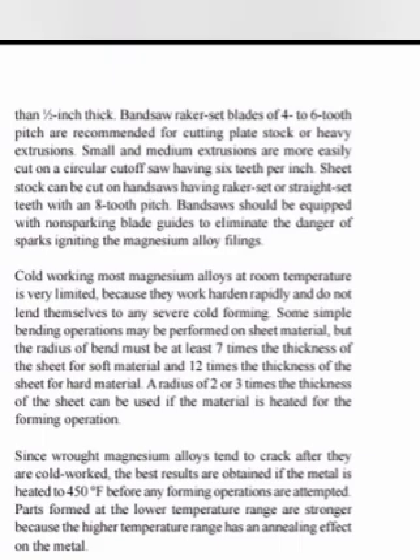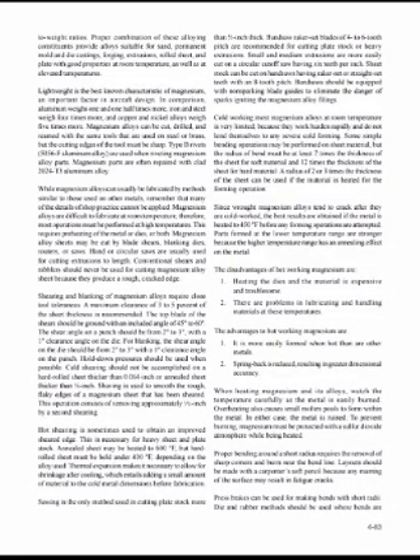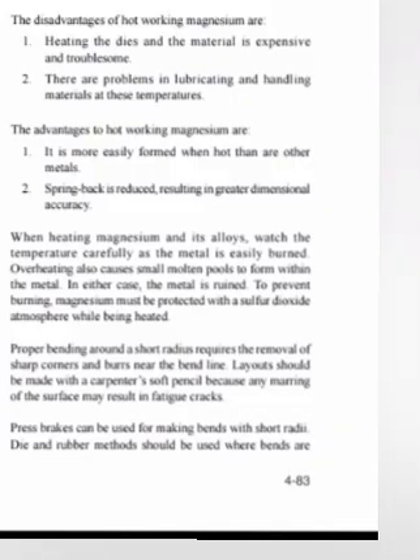Since wrought magnesium alloys tend to crack after they are cold worked, the best results are obtained if the metal is heated to 450 degrees Fahrenheit before any forming operations are attempted. Parts formed at the lower temperature range are stronger because the higher temperature range has an annealing effect on the metal. The disadvantages of hot working magnesium are that heating the dies and the material is expensive and troublesome. There are problems in lubricating and handling materials at these temperatures.